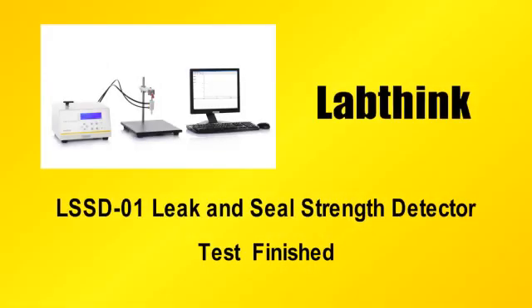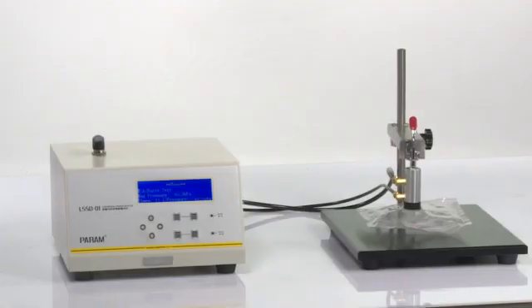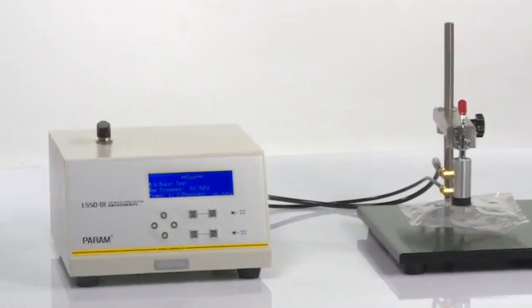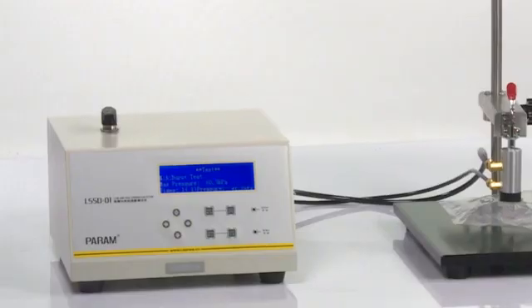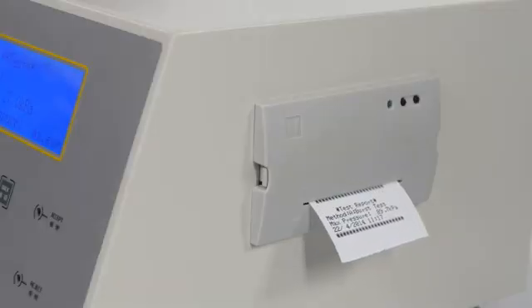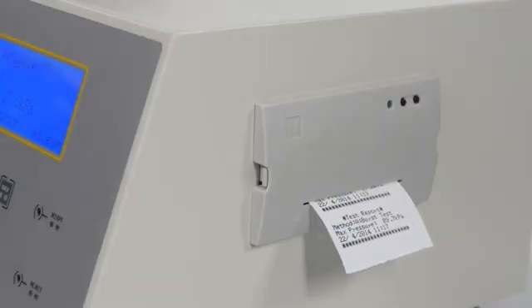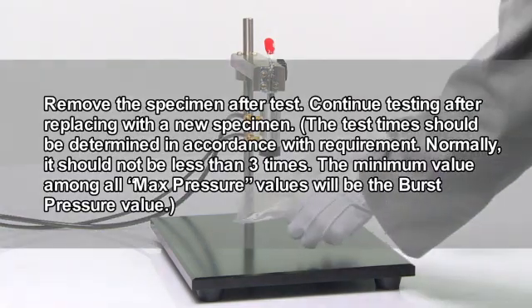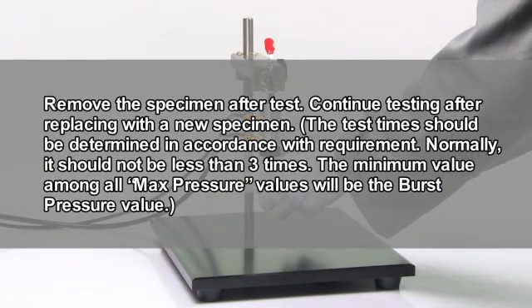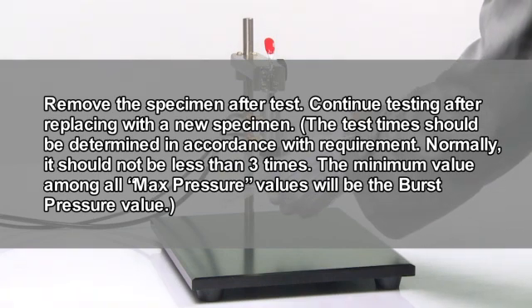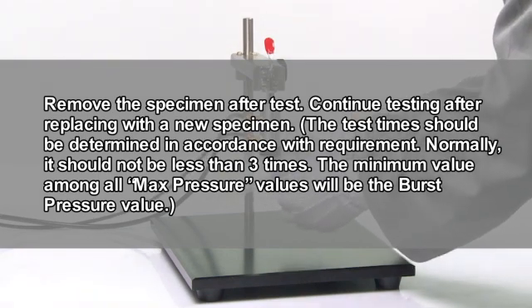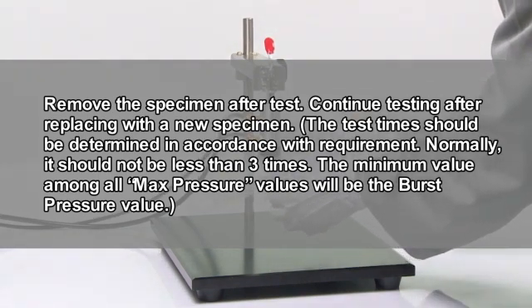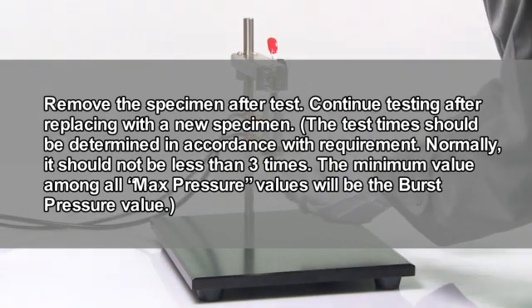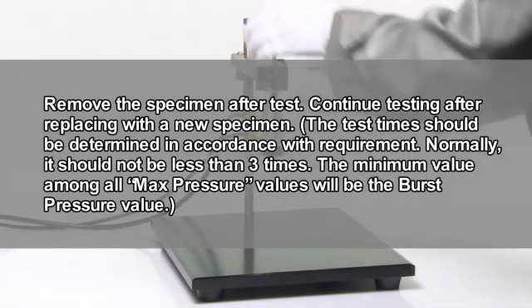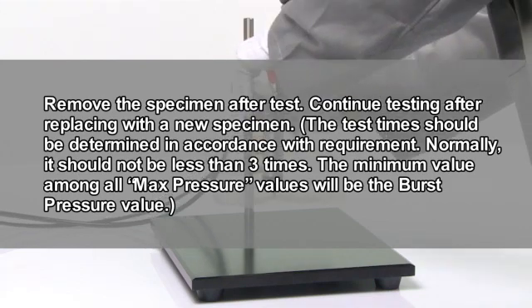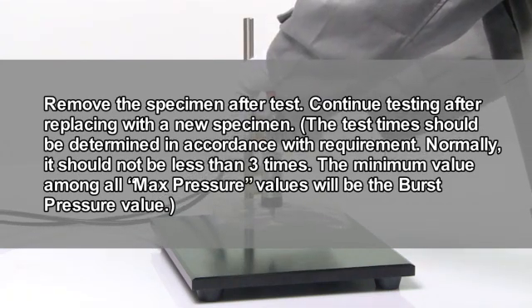Test finished. The screen will display the max pressure after specimens burst. Record or print the value. Remove the specimen after test. Continue testing after replacing with a new specimen. The test time should be determined in accordance with the requirement. Normally, it shouldn't be less than 3 times. The minimum value among all max pressure values will be the burst pressure value.